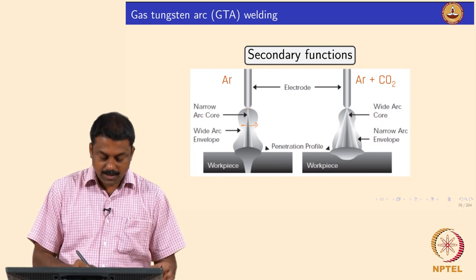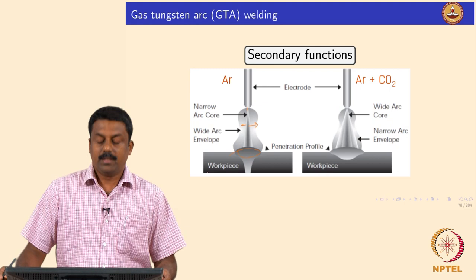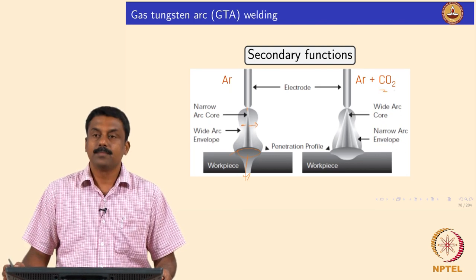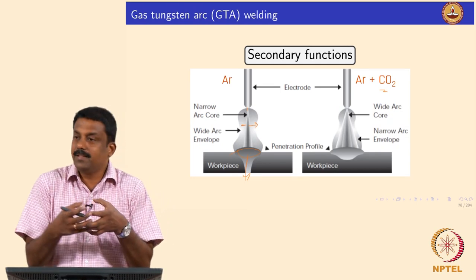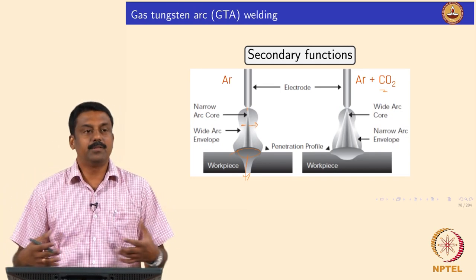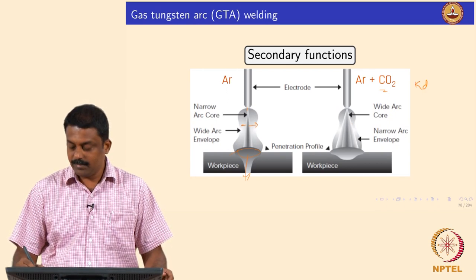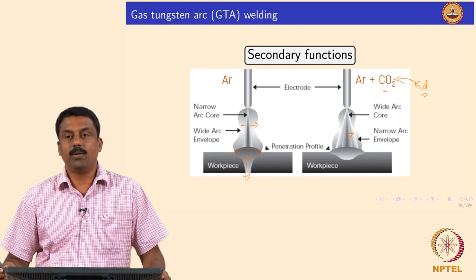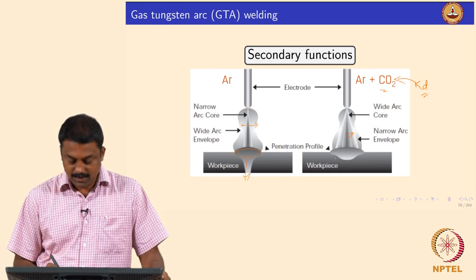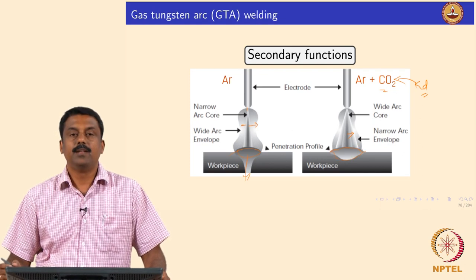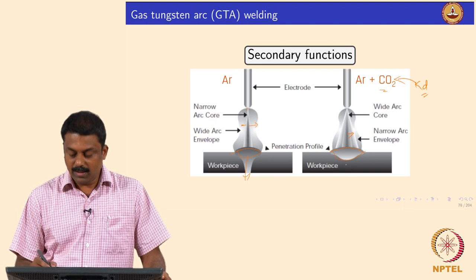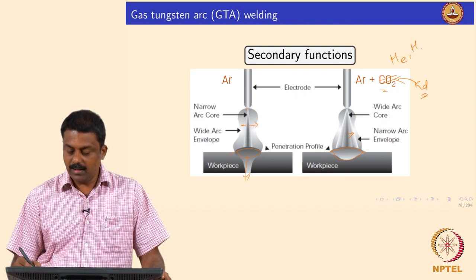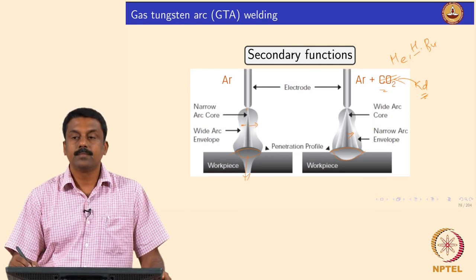With pure argon you have a very narrow arc core leading to deeper penetration. When you mix in CO2, the arc core expands because heat is now distributed by de-dissociation; the thermal conductivity (Kd) term distributes temperature from the core to the outer periphery. During this process you distribute the heat, leading to a wider bead and shallower penetration. The same happens if you replace with helium or hydrogen — instead of Kd, you have a much more effective buoyancy flow.